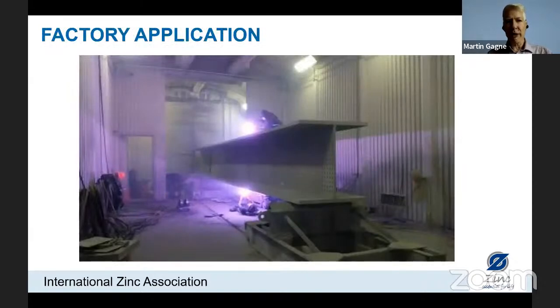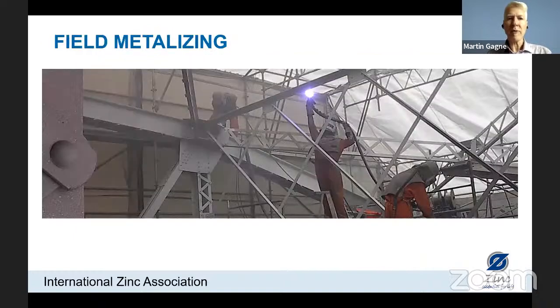So a photo showing some factory application. Here we have two operators, one on top, one underneath, manipulating the thermal spray guns to coat this steel beam. This is a field application. This is a very old bridge. We can see some of the riveted connections. So we can do field repair. This paint has been blasted and removed, and now the thermal spray zinc is being applied.